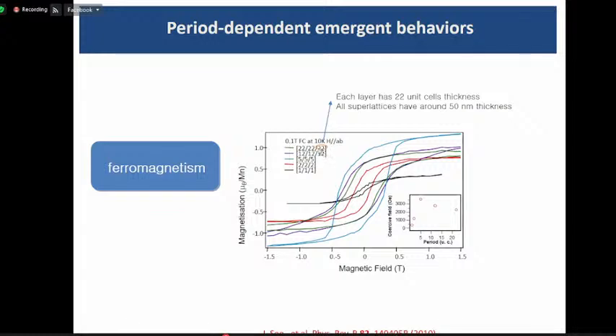Okay, if you see the circle, they say 22. It means each layer has a 22 unit cell thickness. Then we keep the total thickness around 50 nanometers.